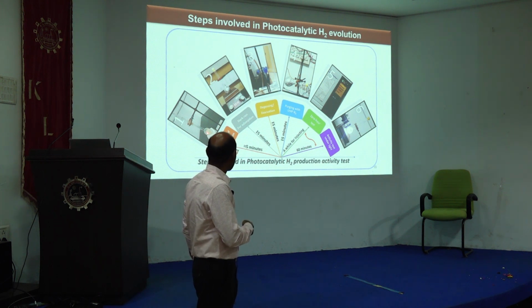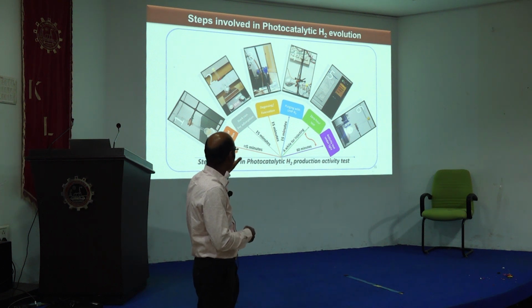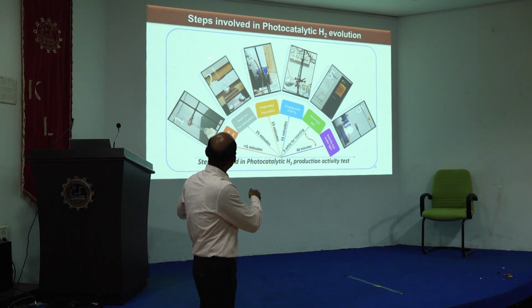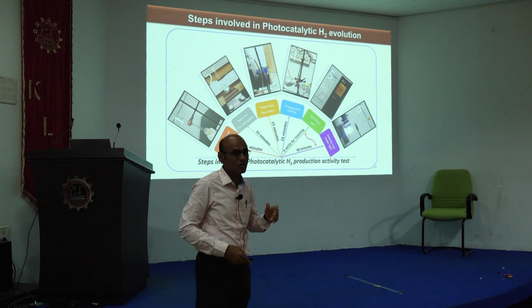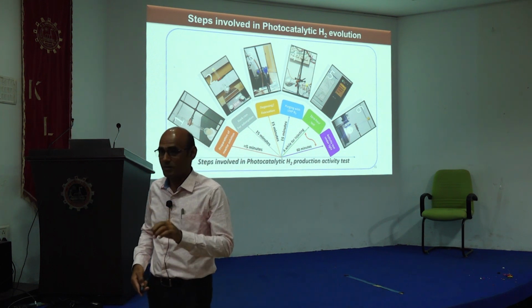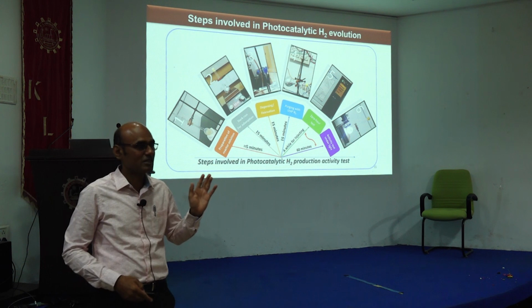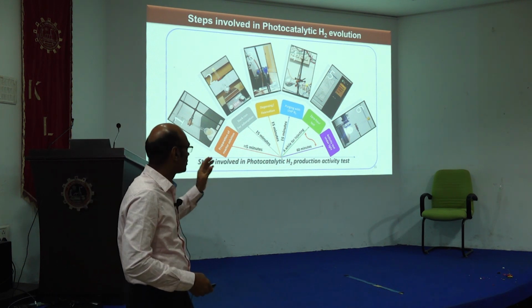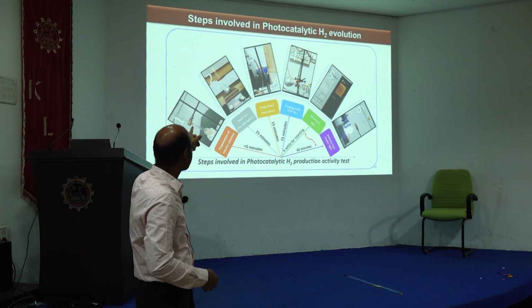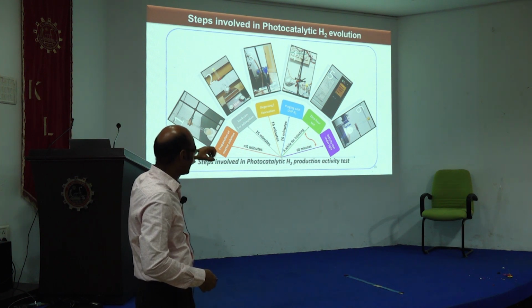So we charge our catalyst in an electrolyte solution. That is mostly either pure water, or water with some sacrificial agent. Then we disperse the catalyst and go for dark adsorption for half an hour. Then it is sealed with a rubber septum, you can see at the top. It's not an ordinary one, it's a specially made rubber septum available from Sigma Aldrich. Each septum is about 120 rupees. It can be used for only 2 or 3 experiments. With the airtight rubber septum, it was degassed.